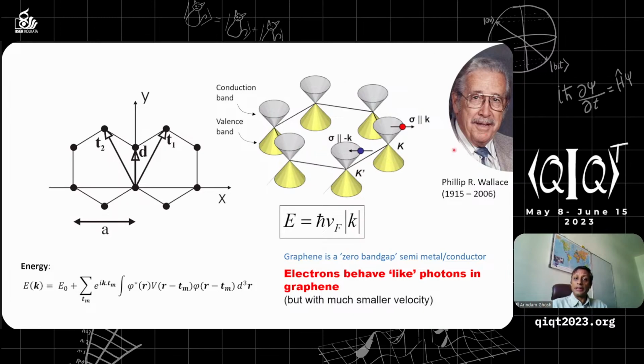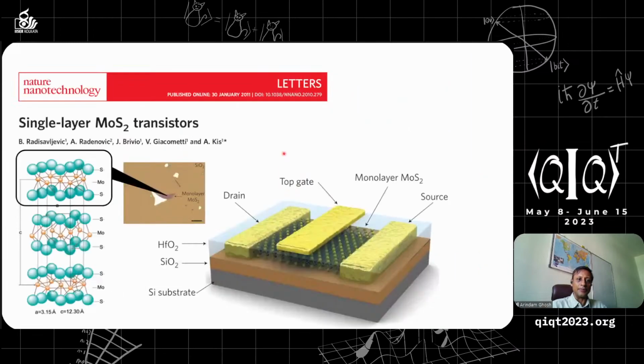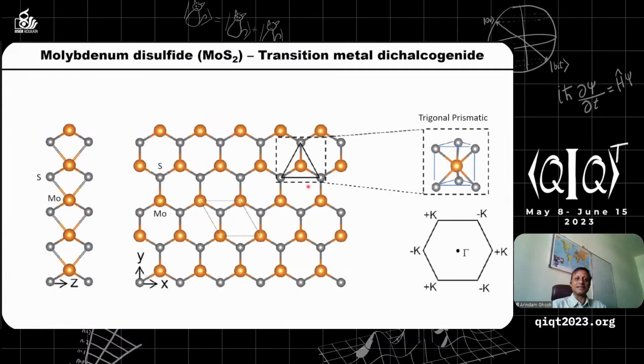Now, graphene is certainly not alone. Another very prominent member is molybdenum disulfide, or transition metal dichalcogenides. The difference between molybdenum disulfide and graphene is, apart from the fact that this is a molecule rather than a single carbon atom, you can still take out one atomic layer of this molybdenum disulfide and make an electrical circuit. Graphene has a conical band structure, which means there is no band gap in graphene. But in the case of molybdenum disulfide, it's a semiconductor.